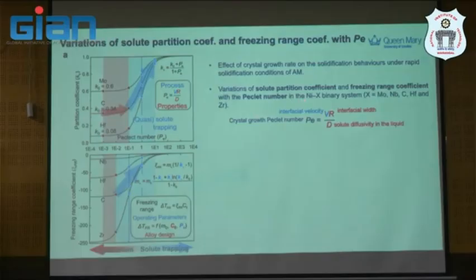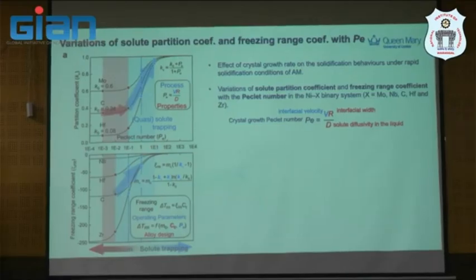There is an interfacial velocity of the growth, interfacial width, and the solute diffusivity in liquid. And then if you use this as an index, you will see that if you have the larger Peclet number, that means you probably promote more interfacial velocity. The melt pool travels faster. So that means if you quickly bang a lot of energy into your system, you will fall into something called the solute trapping zone. That means it's not equilibrium anymore.